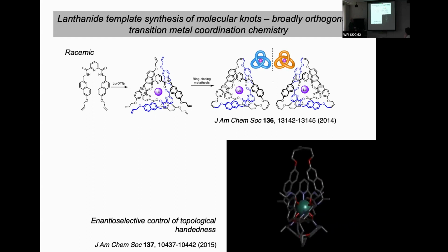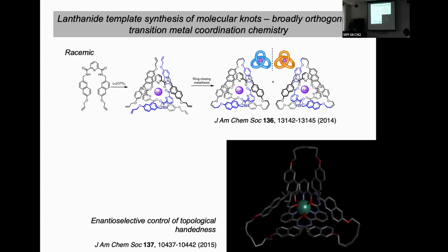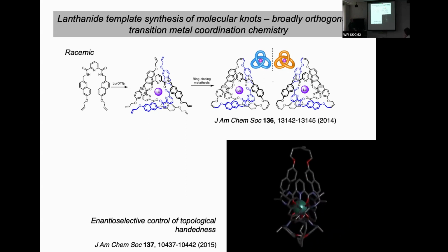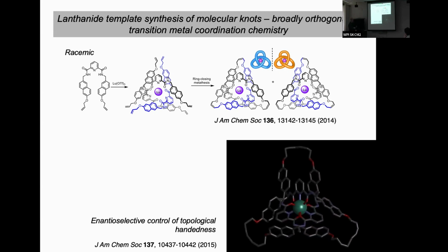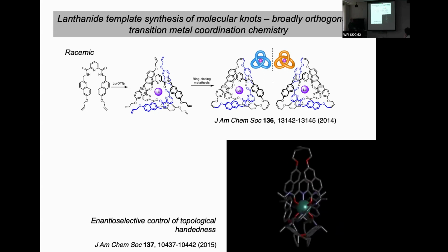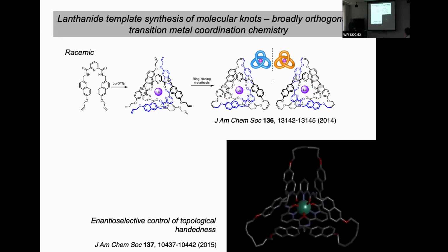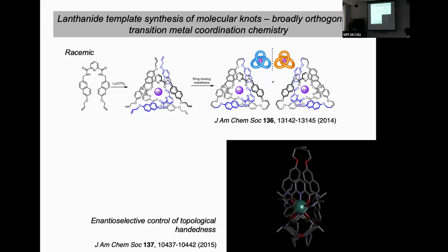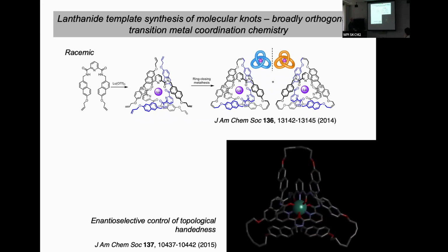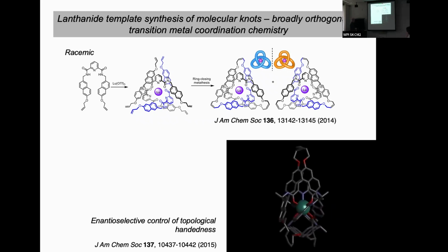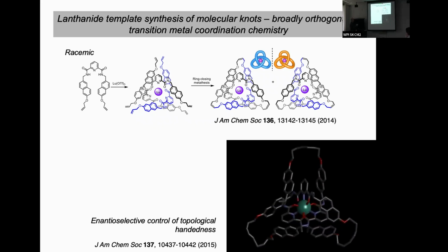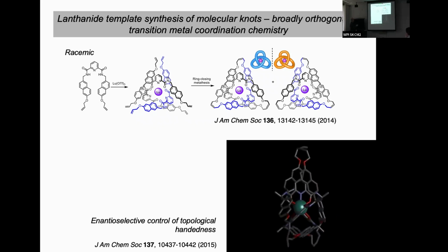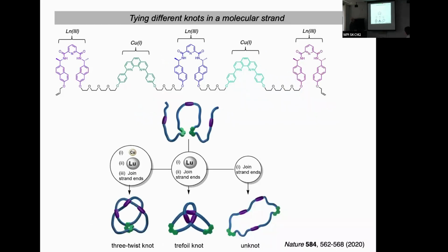However, if you introduce a chiral center on these ligands, you can actually get just a single topological enantiomer of the knot. So just the knot having either lambda helices or delta helices. So a single topological enantiomer of the knots. And this is an X-ray crystal structure. Sorry, it's a bit dark to see, of just a single enantiomer of one of these knots. So this is nice because the coordination chemistry of lanthanides is generally rather orthogonal to transition metal template chemistry or coordination chemistry. So that means that we can mix the coordination binding groups in a single ligand strand, as we've done here, to produce new kinds of effects.